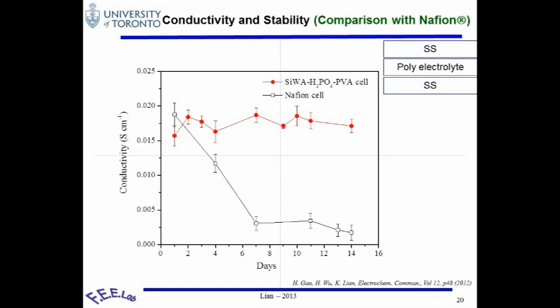So at the beginning, the pristine condition, what we see is that the Nafion looks better, it performs much better. However, if we just leave it in room temperature, in the ambient condition, the Nafion conductivity decreased very quickly. However, the material that is solid conductive in the solid state is relatively stable over about 2 weeks' time. So that gave us some idea of where our material stands in terms of stability.